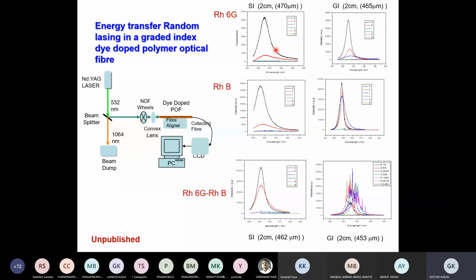We not only add the high refractive index material, but also some gain medium like rhodamine B, rhodamine 6G, etc., which are fluorescent dyes. So this is a comparison between step index and graded index, step index and graded index with another fluorescent dye, and step index and graded index with a combination of these two dyes. And what we can see here is significant narrowing of emission in the graded index when compared to the step index.